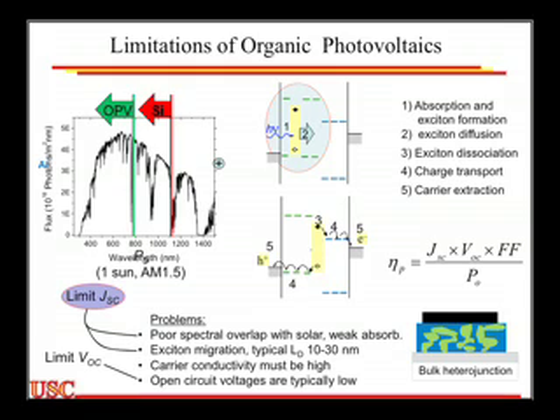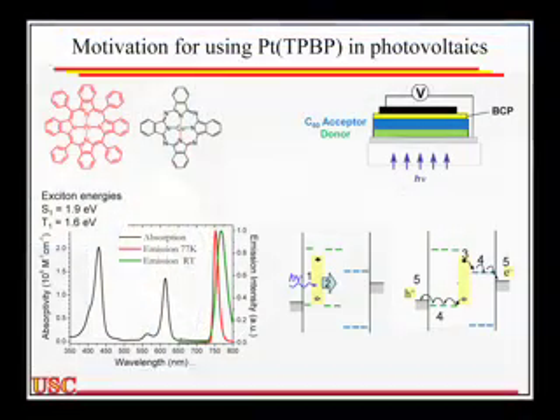Now, fortunately, there's a solution for this, and it's called the bulk heterojunction. If instead of using a lamellar structure, where I've got a single layer of donor and a single layer of acceptor, I use something like this, a sort of bicontinuous network, now the exciton doesn't have to diffuse through a thick layer, it only needs to diffuse through this finger. And so long as this distance is on the order of the exciton diffusion length, you can do pretty well. And so now, in a bulk heterojunction device, you can actually get quite high short circuit currents because now your light collection is not limited by the exciton diffusion length.